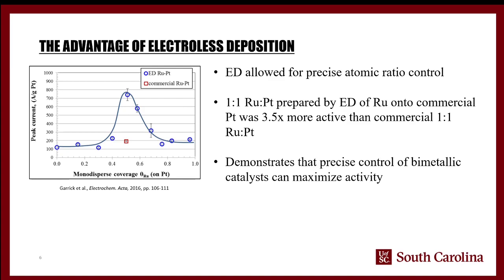It also shows that the electroless deposition allowed for very precise atomic ratio control, and so that lets you see that there's this sort of peak that forms here, with a very precise ratio needed to achieve your maximum activity. If you're a little bit off, even 55%, 45%, you're going to see about 25% reduction in activity. And so the exact ratio actually does matter a lot.